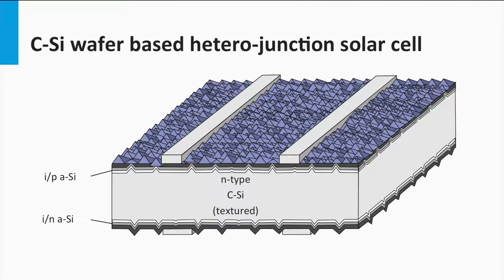How do the charge carriers travel to the contact? The conductive properties of the p-doped amorphous silicon are relatively poor. In the homojunction solar cells, the diffusion to the contacts takes place in the emitter layer. In contrast, in a HIT solar cell, this occurs through the transparent conductive oxide material, like an ITO, which is deposited on top of the p-doped layer.